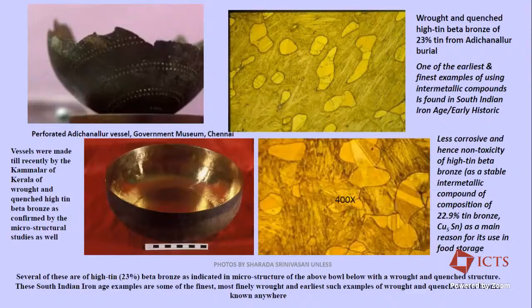And also these kinds of extremely highly wrought vessels. I mean, the rim thickness here is no more than 0.1 to 0.2 millimeters thick. And to have done this by hand is simply astonishing. And plus the strainer has these very, very tiny perforations. And you see here this quenched beta bronze structure.